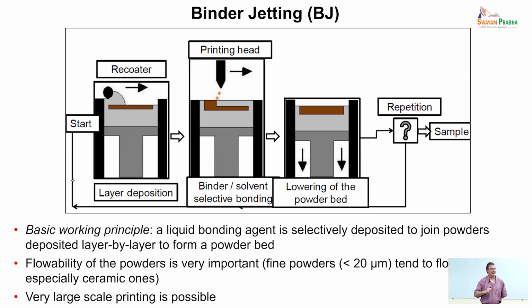In this case, you can use inkjet printer heads, which have a resolution of a few hundred dpi, dots per inch. And so the quality of the surface can be quite good for the printed object. And what you are jetting is basically a polymeric binder, a diluted polymeric binder that can go through the small nozzles of your printer head.